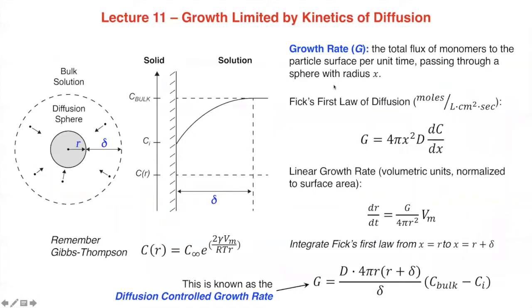models. So we set up this kinetics of diffusion picture where you have monomer diffusion to a sphere and you get this depletion region that has a width. And the width of that region is related to how fast the surface reactions happen. If the surface reactions, where the monomers reach the particle and stick instantly, if that process is really fast, then you can get these depletion regions and you can get diffusion limited growth kinetics.